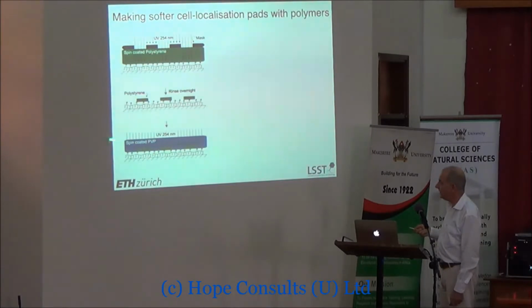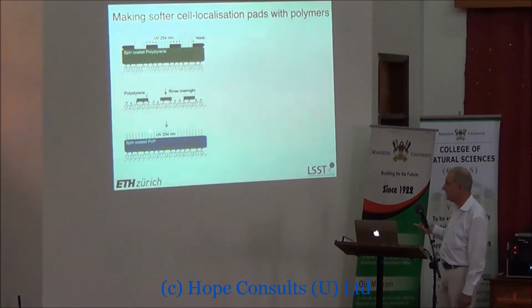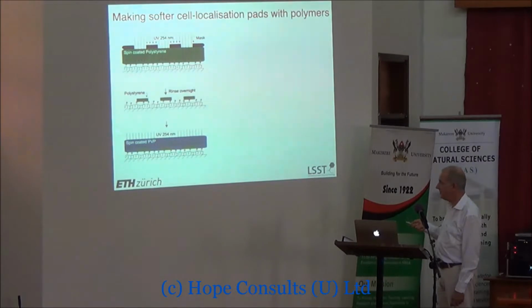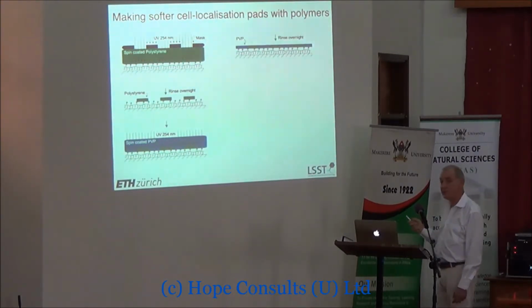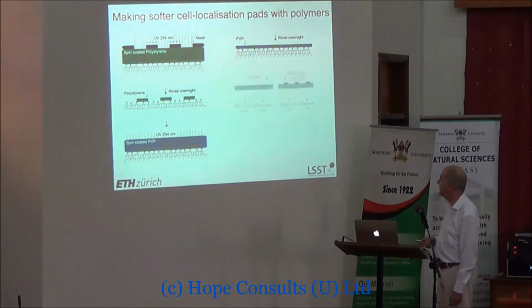We then do the whole thing again. We spin coat another polymer on top of it, in this case polyvinyl pyrrolidone, which is very hydrophilic and very resistant to protein and cell adhesion. And we expose it without a mask, and all the areas that weren't hit before with the UV light now become activated, and they connect to the PVP. Then we wash away the excess PVP, and we've got two polymers in a pattern on the surface. And then we use it for cell experiments.